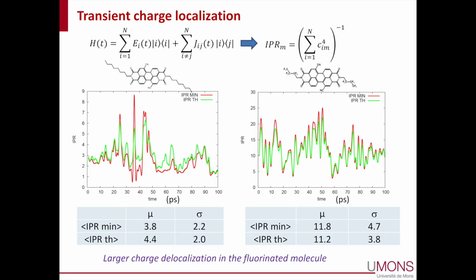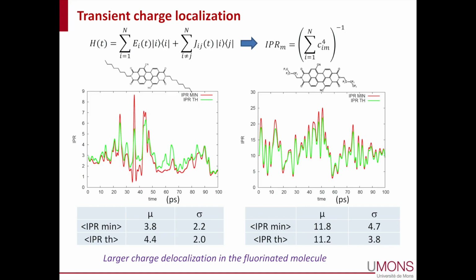So what we do, we use the usual model with site energy depending on the environment, quantum mechanical interactions between all the molecules. You build large systems, large supercells of those crystals. You do molecular dynamics simulation. This is classical MD. And then you can solve this Hamiltonian as a function of time and track how the charge delocalizes as a function of time. So this is a direct measure of the transient localization that we've heard previously. You can see how the charge breathes with time in the two molecules.